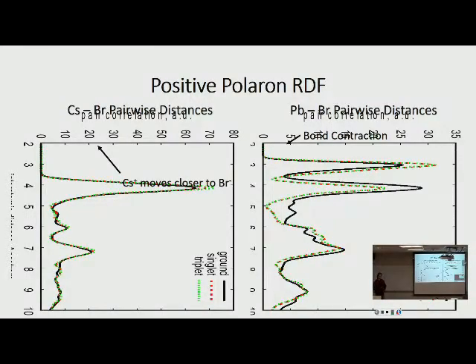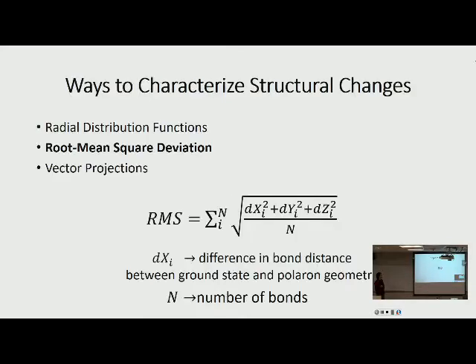So we're good on radial distributions. Negative polaron to be determined. And then a more statistical method that Dimitri suggested is root mean square. Basically, if you have a reference number, you can always do a root mean square. You take the difference of whatever you're trying to measure and square it, so you cancel out the negative amplitudes, then normalize it to the number of things you're measuring and take the square root. In this case, dx, dy, dz is just the difference in x, y, and z components for the same bond for the ground state and polaron.